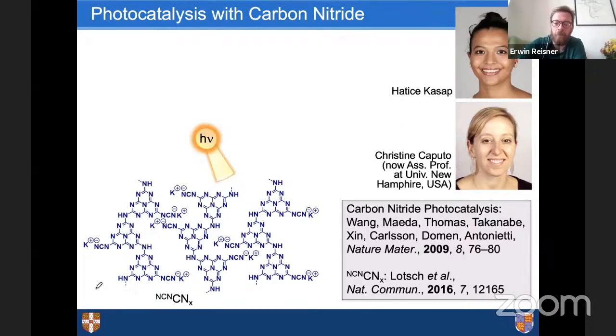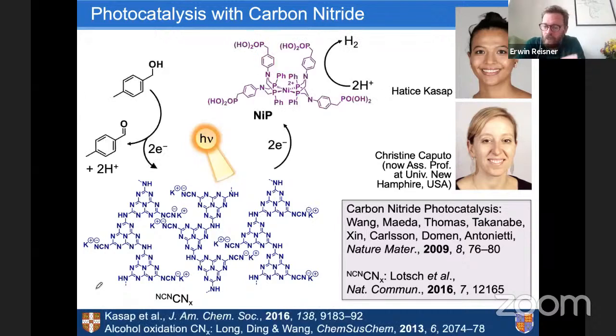So what we found is we took this carbon nitride, and already before we got into biomass, we became interested in exploring organic systems more broadly. And what Tietje achieved here was actually a nice system where, upon photoexcitation of carbon nitride, she could use these electrons to reduce protons to hydrogen with this molecular nickel bis-diphosphine catalyst. So this is a classical Du Bois catalyst with two phosphonate groups. And we found that this really forms a nice interface, in fact of unknown nature, but it works really well in the system to make hydrogen. And the electrons can be sourced from classical sacrificial reagents, but also from this benzyl alcohol that forms benzaldehyde.